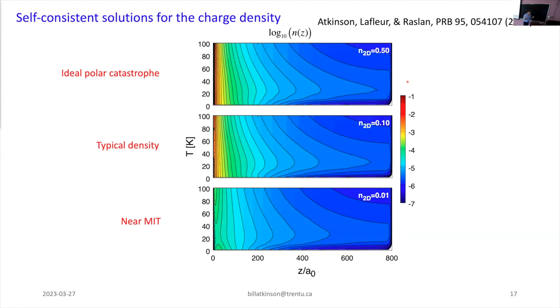That actually does show up in certain cases. There are certain people who've grown different cap layers other than lanthanum aluminate, and they get something close to a half electron, but it's not typical. Much more typical is something around 0.1 electron per 2D cell. And you can gate these things all the way down to a metal insulator transition that happens at around 0.01 electron per 2D unit cell. And that's the case on the bottom here.